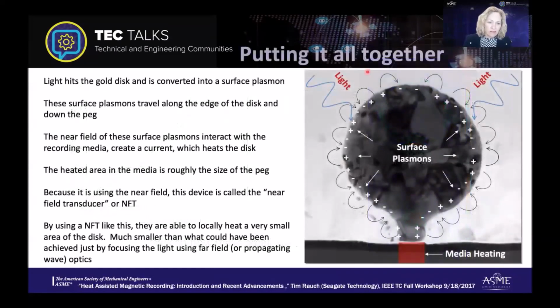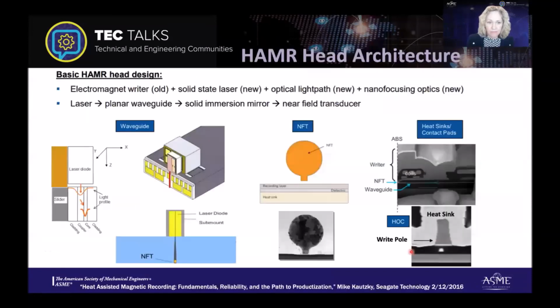So you put that all together: you have the light focused onto a gold disk that interacts with the electrons and creates surface plasmons that travel along the surface down to the peg. At that surface, the electromagnetic field, or the near field from the surface plasmons, can create a current in the media and heat that very small spot, just where that near field is interacting with the disk. This is a much smaller spot than we could create if we tried to focus that laser light onto the disk. So how do you actually integrate that into a head?